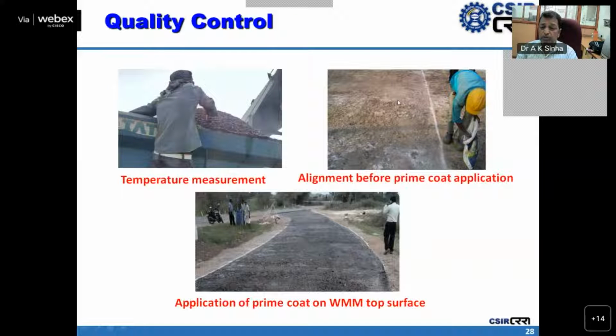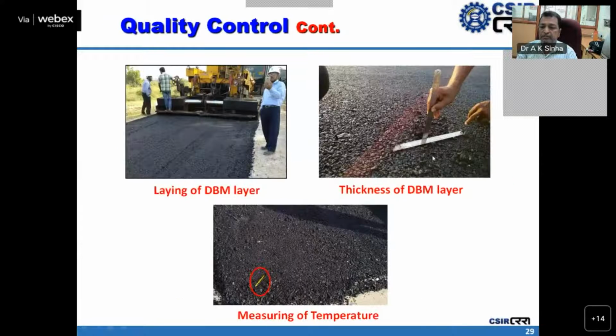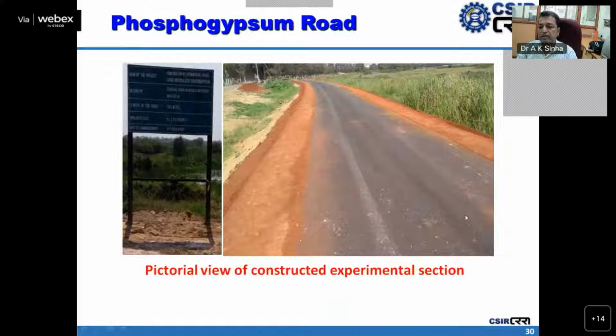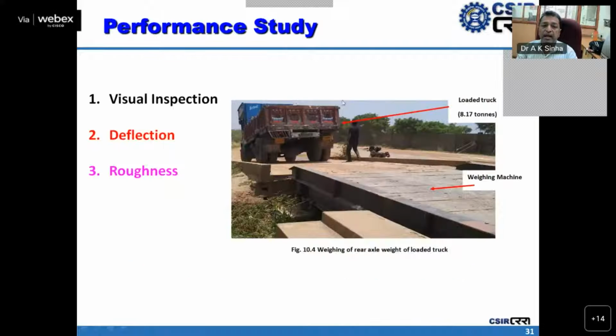For the higher layers, bituminous layers, quality control was done at the hot mix plant. This is the alignment, the first pictorial view of the proposed road, and this is during the construction, where temperature, thickness, and all those parameters were measured. And this is the pictorial view of the finished experimental test section using phosphogypsum. And these are the details of the project, which was carried out under the supervision of CSIR, CRRI, and different agencies.